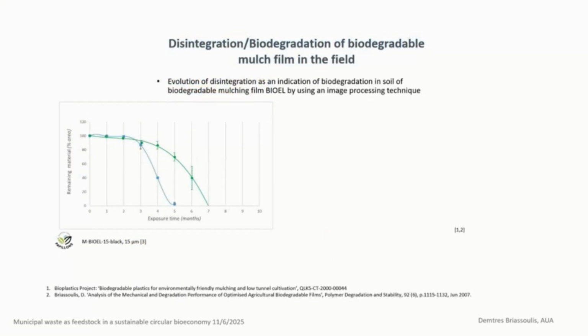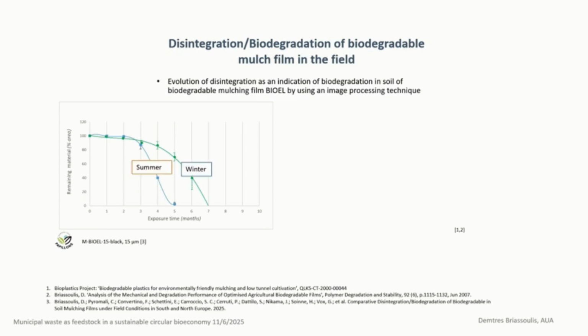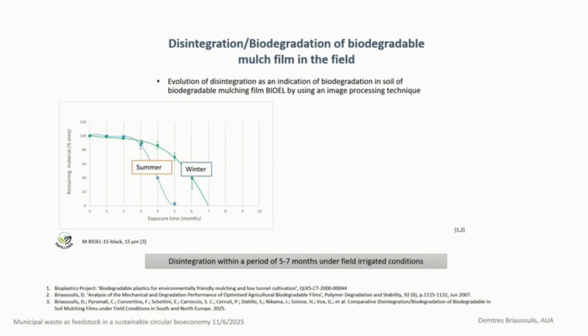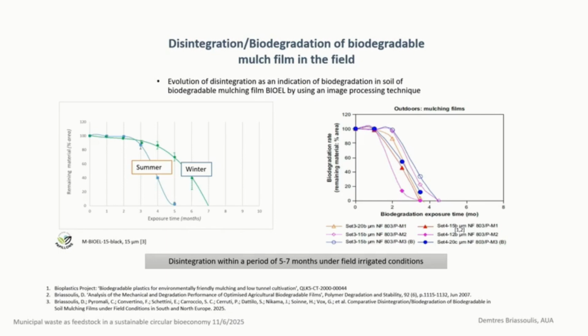Here you see the results of a recent experiment in the experimental field of the Agricultural University of Athens. You see the disintegration rate in the field of a film incorporated in the soil during summer and during winter. And the result shows full disintegration within a period of 5 to 7 months under irrigated conditions. It's interesting to compare these results against the results of another project 20 years ago in the same experimental field, made of a similar but not the same grade of starch-based mulch film with lower bio-based content at that time, a different grade, but we have similar results.